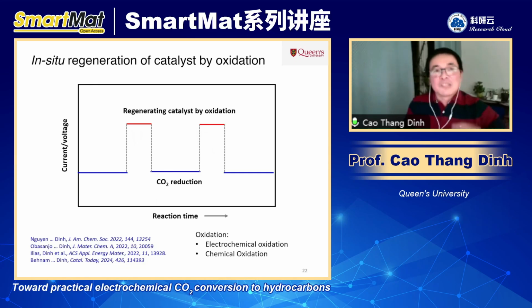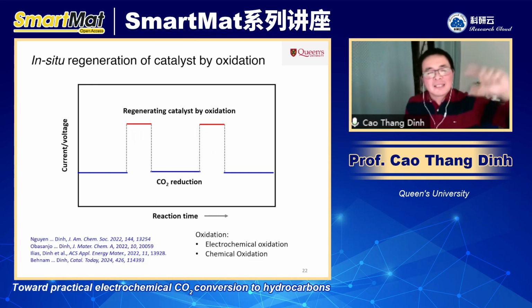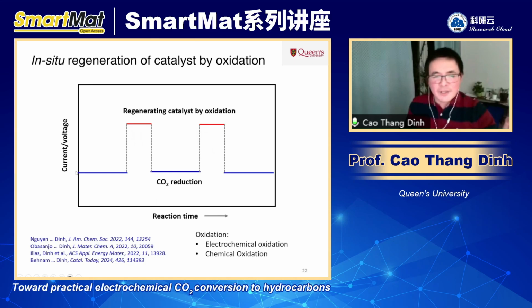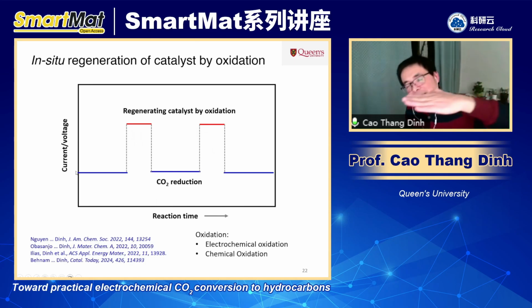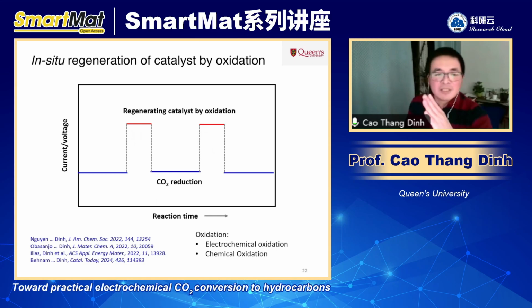So it's kind of like you alternate the current. Let's say if this is the current, then you apply the current for CO2 reduction. Now, after some time here, you oxidize the surface, right? So you control the current, or you can control the potential, to oxidize the surface for some time here, and then you reduce the surface again, turn it back into the metallic state, right? So you can just repeat that.